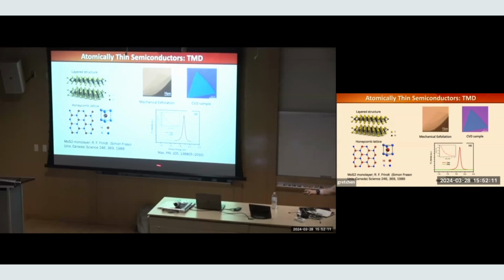So this is one of the early papers. The green light represents photoluminescence coming from a bilayer of this MoS2. And the red light is actually a single layer. Between bilayer and single layer, light emission becomes 100 times more efficient. So what happened there? This peak is what we call the exciton peak. And what's an exciton? Okay.